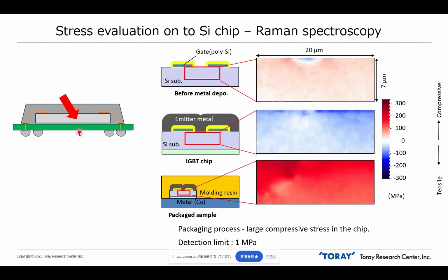It's also important to evaluate the IC chip itself. Raman spectroscopy is very useful to evaluate stress in semiconductors. In this example, before packaging, the silicon substrate has a low magnitude of stress, but after putting on the mold resin, the silicon substrate shows a large degree of compressive stress. So by using Raman spectroscopy, we can get information about the effect of mold resin on the IC chip, also with micrometer-order spatial resolution.